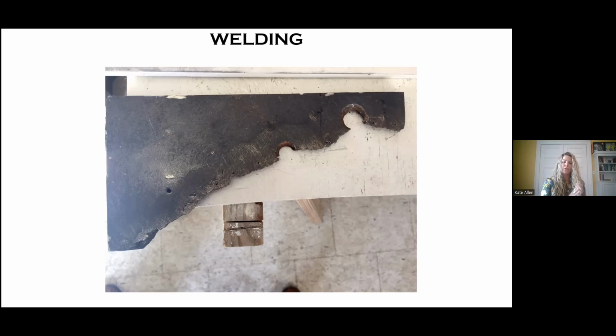But too much welding creates hardening. We found this failed weld at the Capitol, cut out the damaged section, replaced it with a Dutchman, and stitched it in.